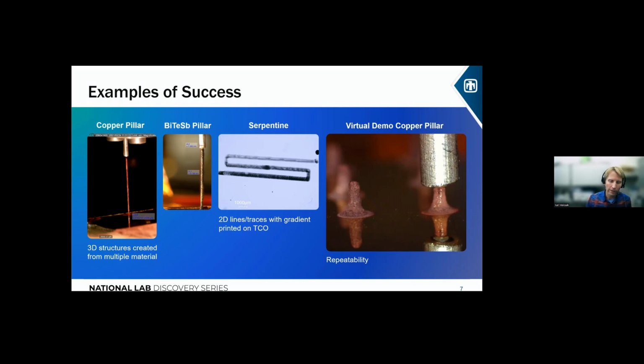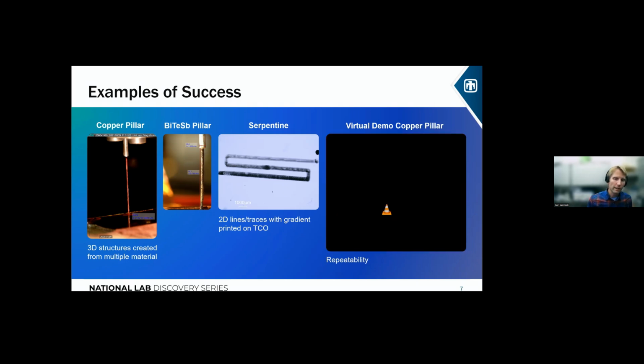And that meniscus, compared to what's currently been published or in research as far as meniscus confined electrochemistry or meniscus confined additive manufacturing or 3D printing, is that this meniscus that you're seeing right here is actually flowing. So it's flowing to reduce inefficiencies in the deposition and to allow for uniform material properties to be deposited. That flowing meniscus also has other benefits. You can switch out potential materials quickly, rinse. You can do a range of things by having the electrolyte constantly flowing. And this also allows for fairly smooth surfaces to be created, potentially shiny surfaces we've shown in instances. So you can really tune structures by tuning some of the flow rates and other parameters here. So let's go on to our next slide.